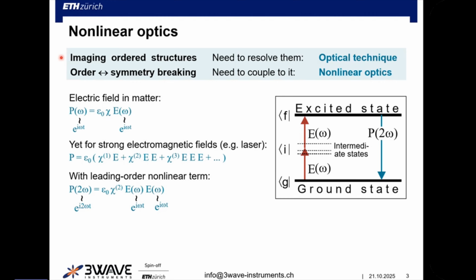So what you do is you send an electric light wave into a material, and we all know electric fields cause polarization. And if the field is strong enough, you do not only get proportionality, so you would get a polarization contribution that goes with E squared or E to the third power, as shown down here. So and these contributions are higher order. They require strong fields like from a laser. If I take the first of these contributions, so the E squared contributions, then you see that because of the frequency dependence of the electric fields, then with 2 photons here, 2 fields here, you get a frequency doubled component as polarization.